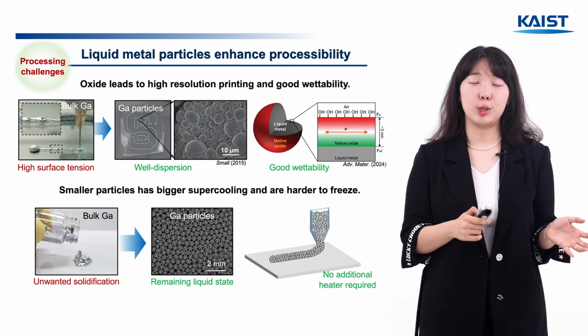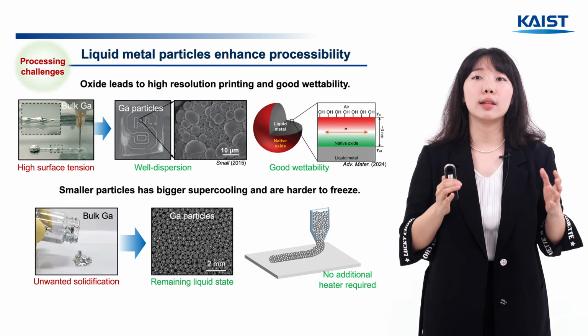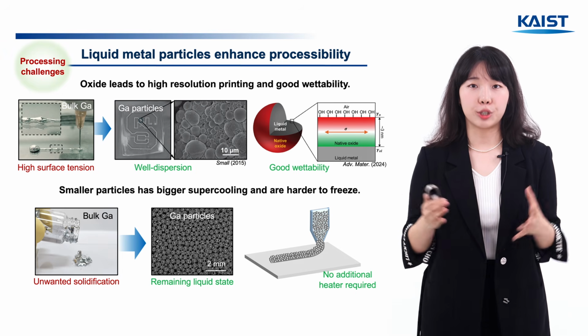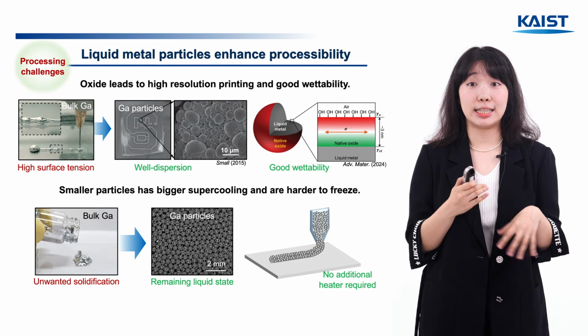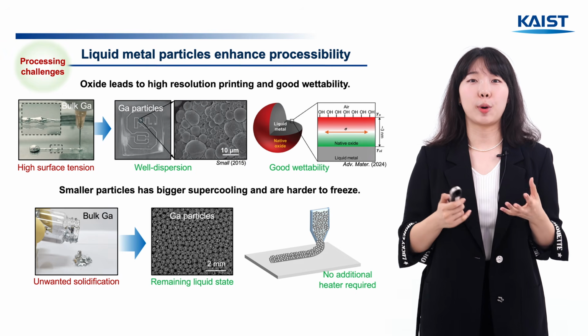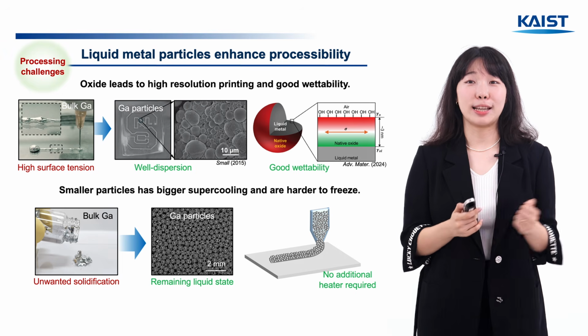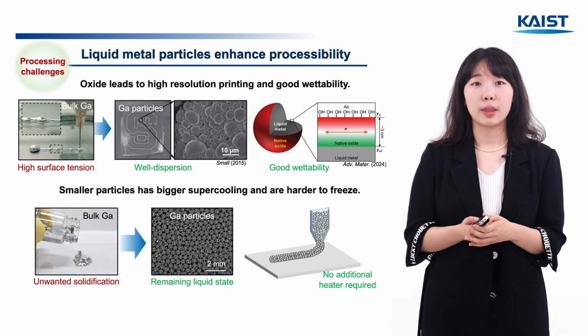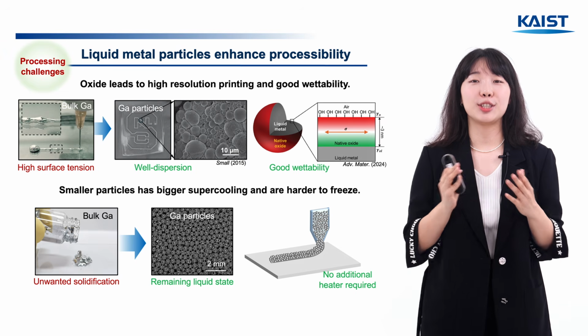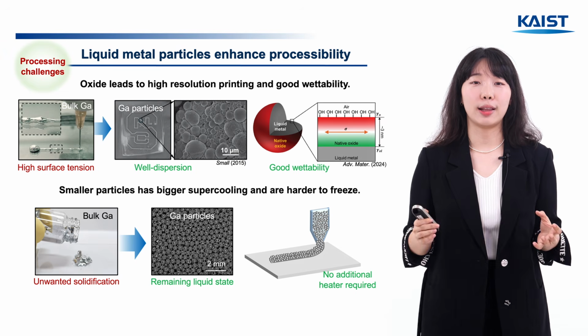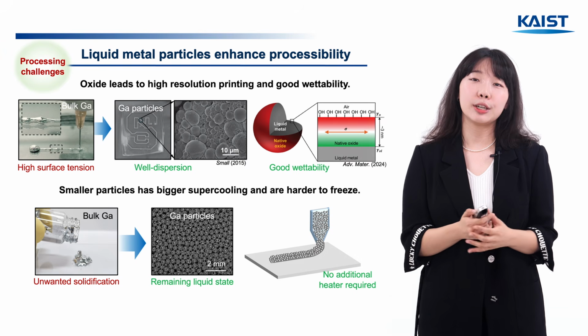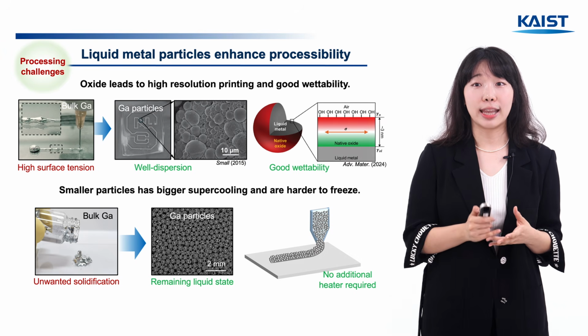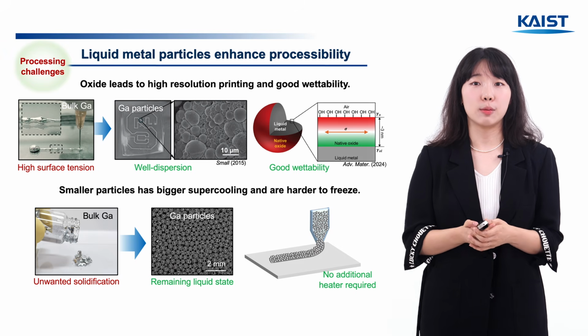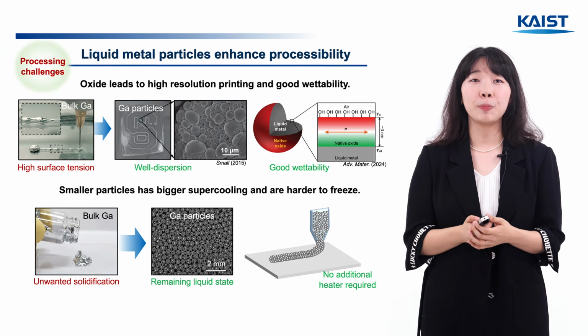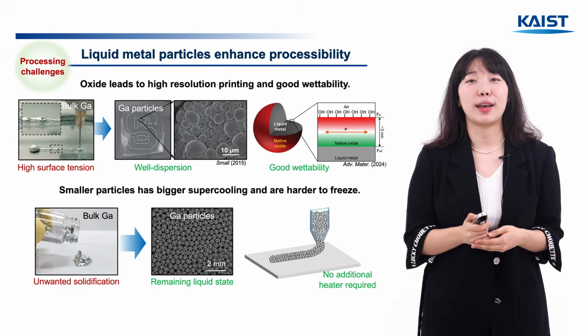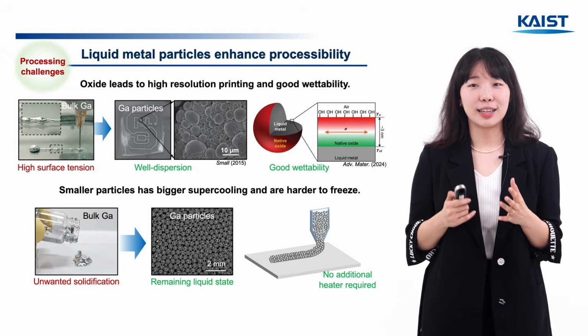Second, turning gallium into particles solves the processing problems. In bulk, its high surface tension makes it merge together, but once it's in particle form, the oxide shell keeps the particles separated. That's what let us print them at high resolution without any clumping. On top of that, the OH groups on each oxide surface make the particles spread well over hydrophilic surfaces. And there's one more benefit. The smaller the particles get, the stronger the supercooling effect becomes, which keeps the gallium from solidifying when we don't want it. The supercooling effect will be explained in detail later in Chapter 1.